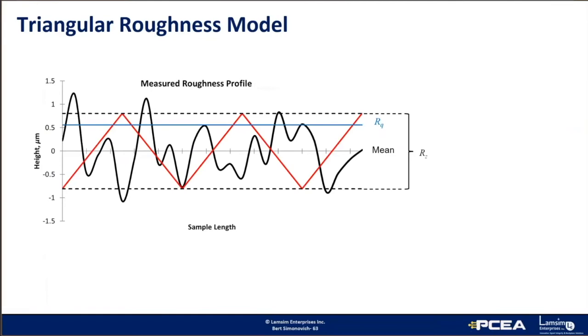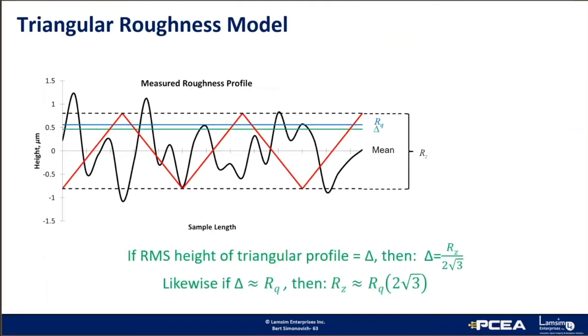Then if we assume a triangular roughness profile with a peak-to-peak height equal to Rz, then the RMS height delta equals Rz divided by 2 root 3. And likewise, if we assume delta is approximately equal to Rq and you need Rz, then Rz is approximately equal to Rq times 2 root 3.